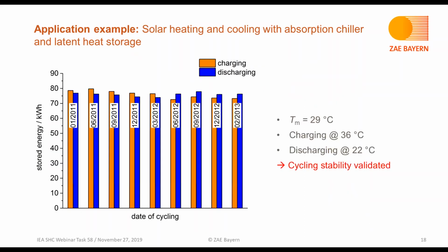This system has been in operation for several years, and here you see the results of the thermal cycling at storage level, again applying a charging temperature of 36 and a discharging temperature of 22 degrees C, and thereby we could validate the thermal cycling stability for this material in this storage configuration.